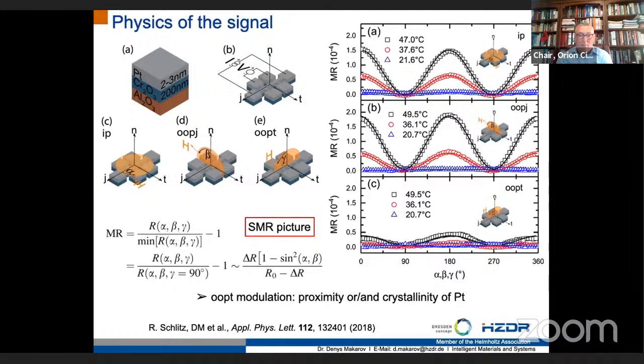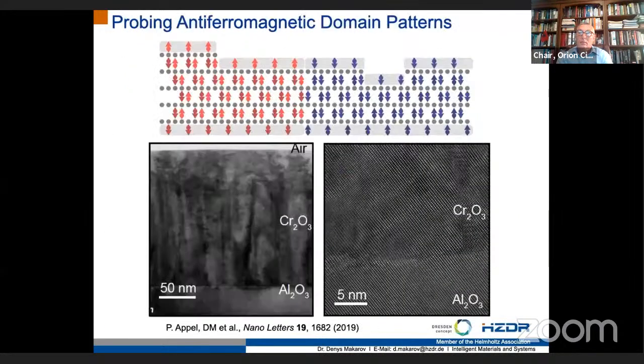Therefore, our current understanding is that the readout signal which we measure in a transversal and longitudinal channel below and above the Néel temperature of chromium oxide is related to the transversal and longitudinal spin Hall magnetoresistance in the platinum, which is interfaced with chromium oxide magnetoelectric insulator. Similar to the ferromagnet, the evolution of this electrical readout can be understood only if you have access to the magnetic domain pattern of the material.